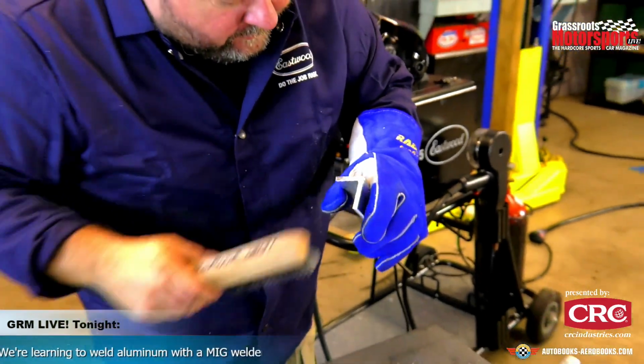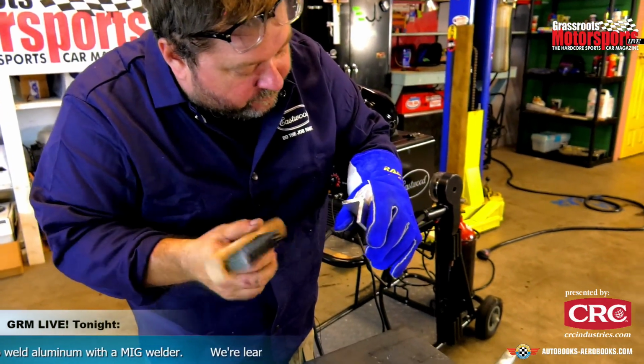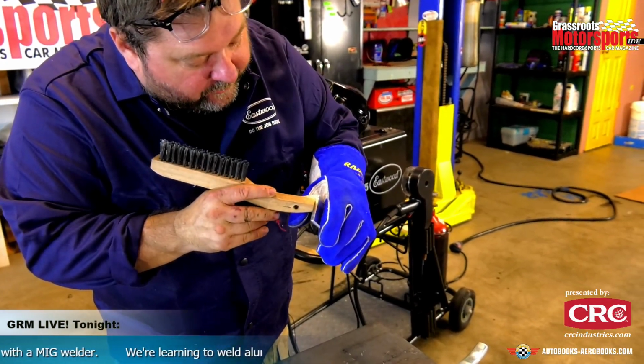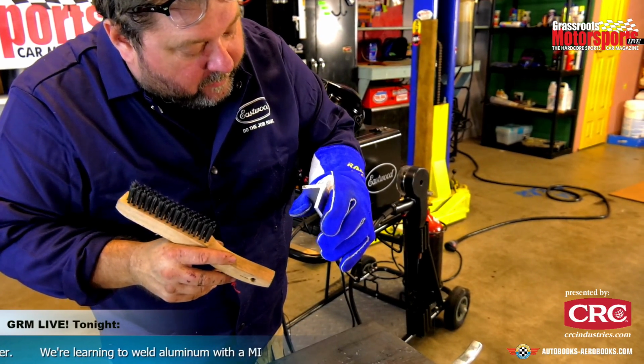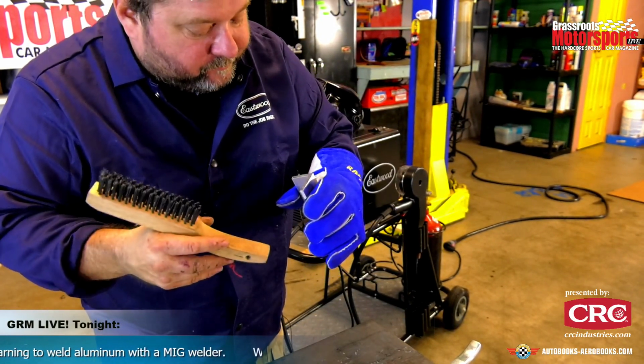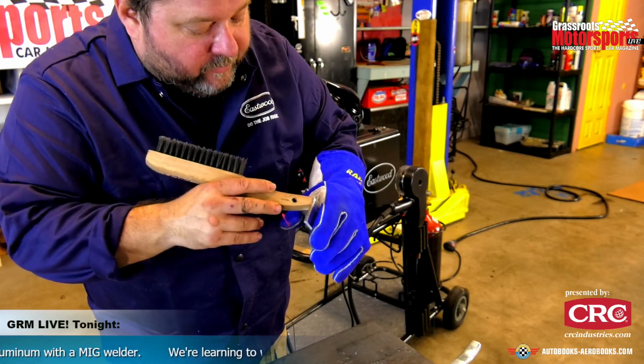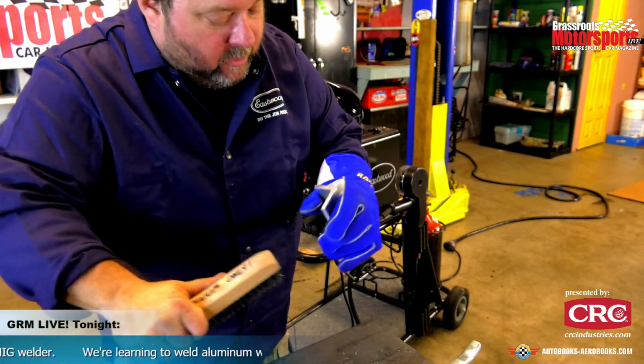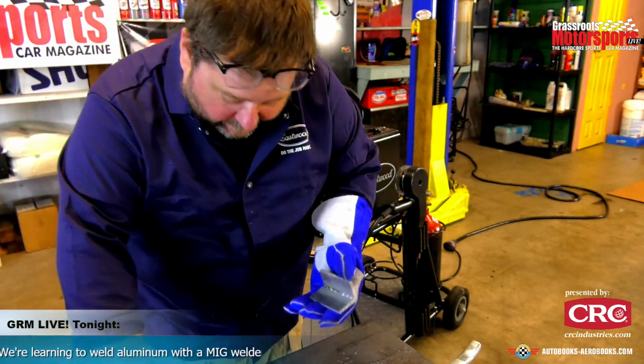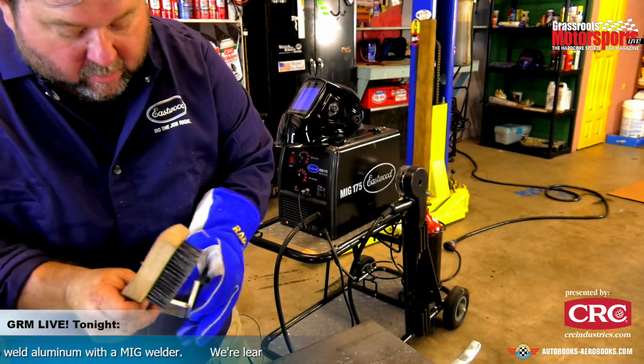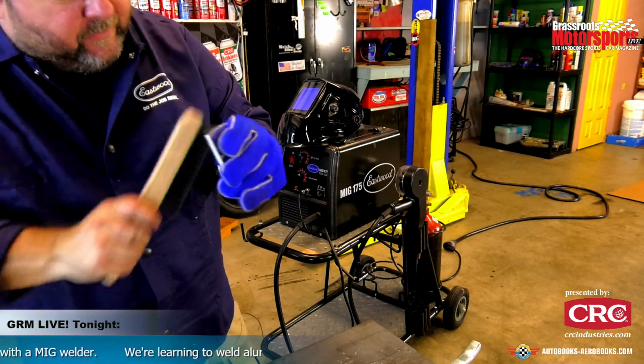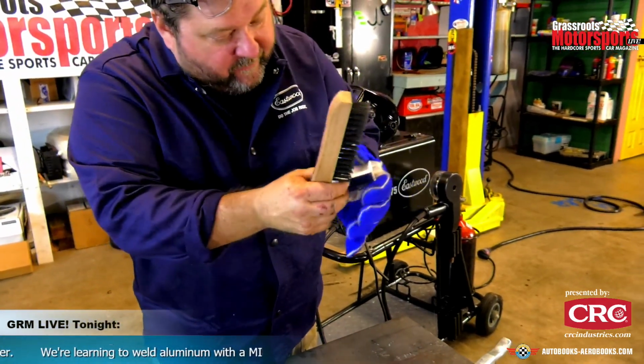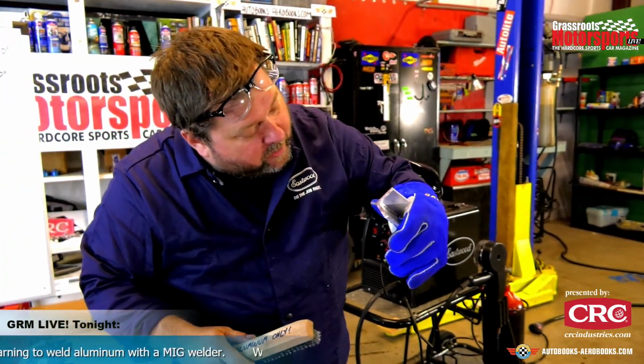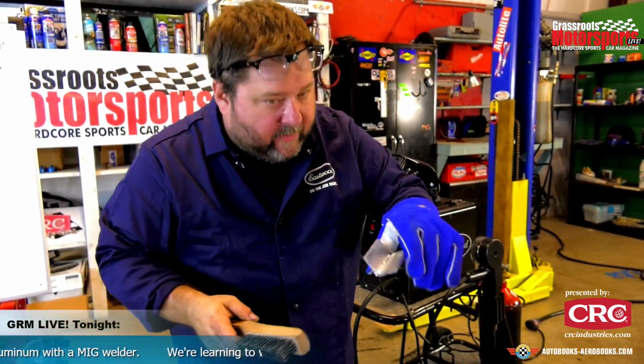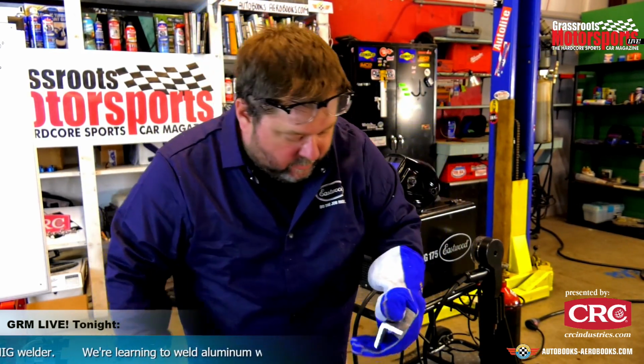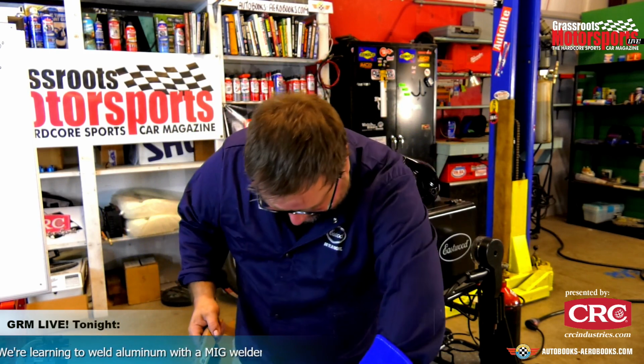But we got penetration. You probably can't see on camera, but we did get penetration about halfway through the base metal. So if we were to do it on both sides, that would be pretty complete penetration for this quarter inch here. And I'm pretty happy with that. Like I say, if we're just talking about this piece here, for my first ever shot, it's still a little warm. First ever shot welding, that's a fairly good looking bead, considering I have no idea what I'm doing.